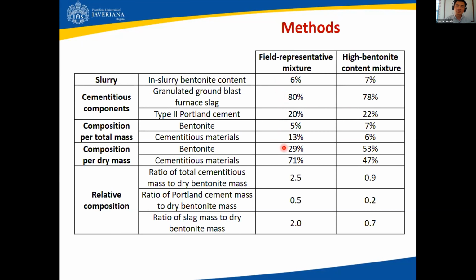However, if we look at those same numbers per dry mass, that is per dry mass of total composition, the bentonite is 29%, and the cementitious material is significantly higher, 71%. That, in fact, is reflected on the three numbers at the bottom, which I showed before. In fact, the ratio of total cementitious mass to dry bentonite mass is in the order of 2.5, whereas that 2.5 number is composed of 0.5 Portland cement and 2 slag. Okay, and like I said, side by side, you can compare with the second mixture that was studied for this particular study.